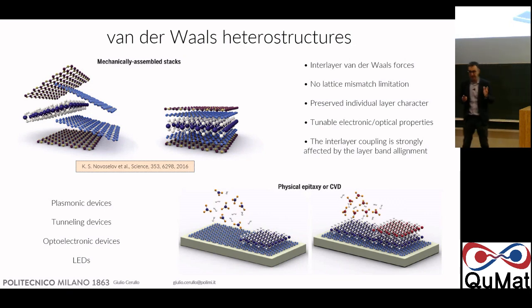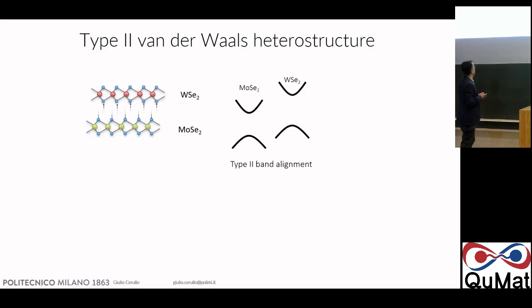Now I want to show you just one example where you have a so-called type 2 heterostructure of two materials, in this case WSe2 and MoSe2. Now, MoSe2 has a smaller band gap than WSe2, as you can see. But they have this so-called type 2 band alignment where the maximum of the valence band is in WSe2 and the minimum of the conduction band is in MoSe2. So what happens in this case? Assuming that you create an exciton in MoSe2, you don't touch WSe2 because you are still below the band gap.